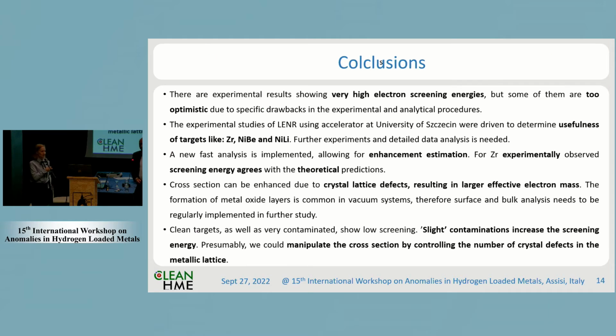Okay, so I will go to my conclusions. We have experimental results showing very high electron screening energies, but we think that some of them are too optimistic. At our University of Szczecin, at the Elbrus lab, we have determined the usefulness of targets like zirconium, nickel-beryllium, and nickel-lithium for cold fusion studies. We implemented a new method for quick estimation of this enhancement, and with that method, the experimentally measured zirconium target screening energy agrees with the theoretical predictions.